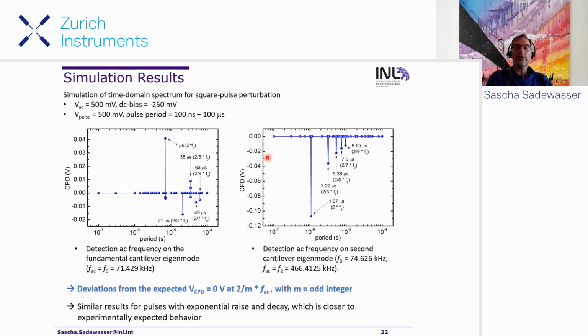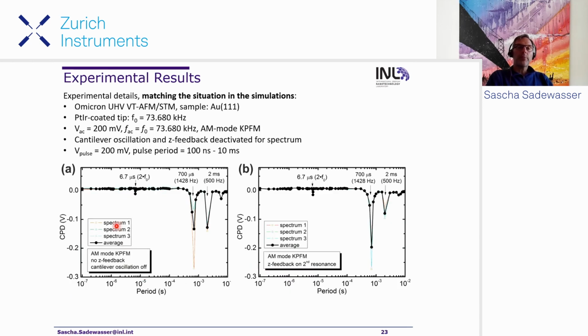And the intensity decreases here. So the initial one is fairly high, but then the second one is already fairly low. So experimentally, we also observed this. We designed a specific experiment where we switch off the cantilever oscillation and the Z feedback to try to simulate as much as possible the simulation conditions. And we do actually observe this effect here at 2 times the frequency of the AC voltage, which we applied at the fundamental resonance, which is very typical of what you do in typical air AFM setups.